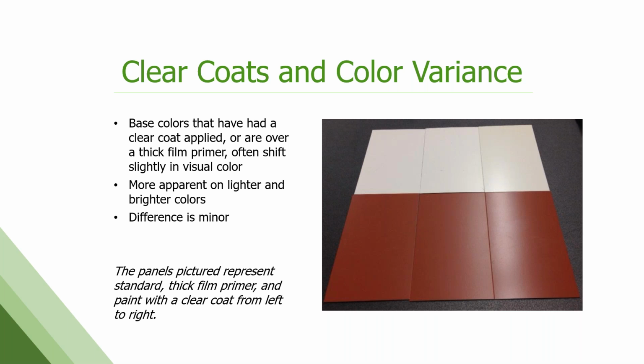But yet another cautionary tale. This one's not so bad. So if you're going to use a clear coat, or if a clear coat is needed for some reason, you do need to understand that clear, while we call it clear, does slightly alter the base color visually a little bit. These clear coats actually have a very, very slight yellow tint to them, which is the UV blockers that are used in them.